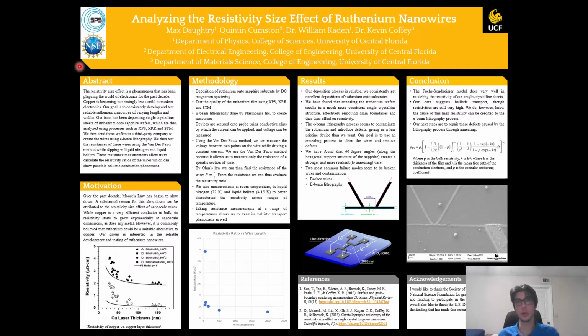And so once we get these nanowire devices back, we can put them onto a probe where we can send constant current through them and measure the voltage drop across a selected length of the ruthenium nanowire. So this here is actually a schematic of what our ruthenium nanowires look like. We basically apply a constant current through this section, and then these two probes that are coming in, which are also ruthenium wires, measure the voltage drop across this section of the wire here.